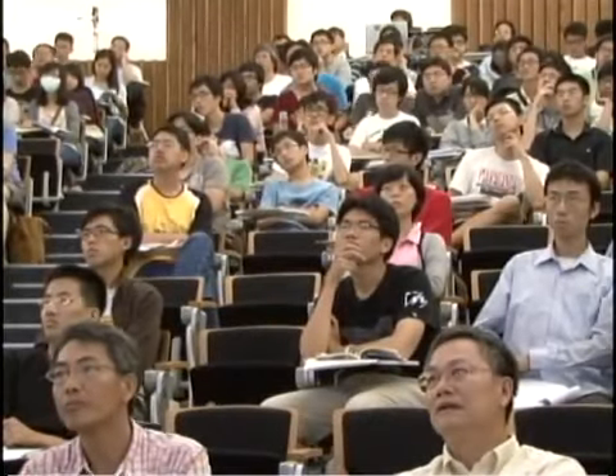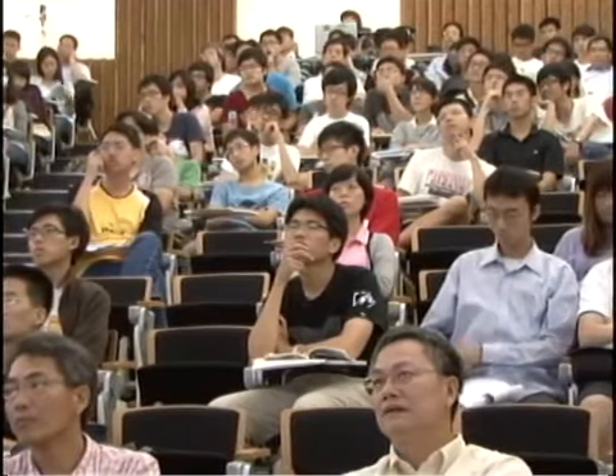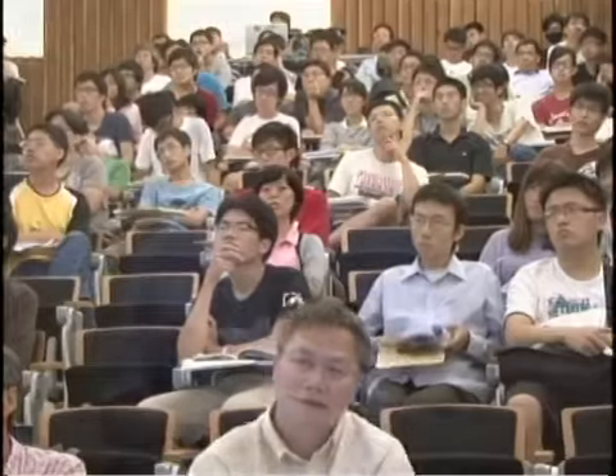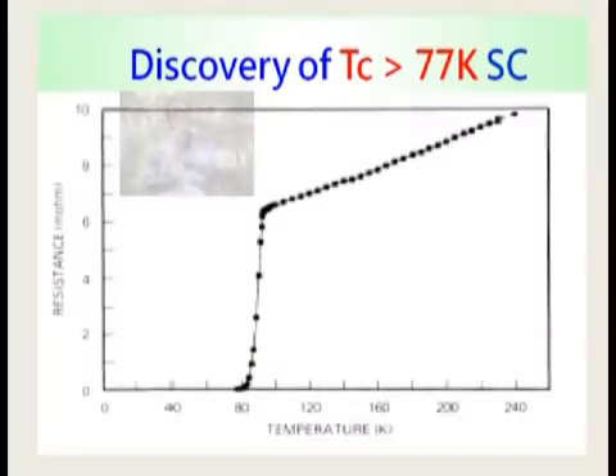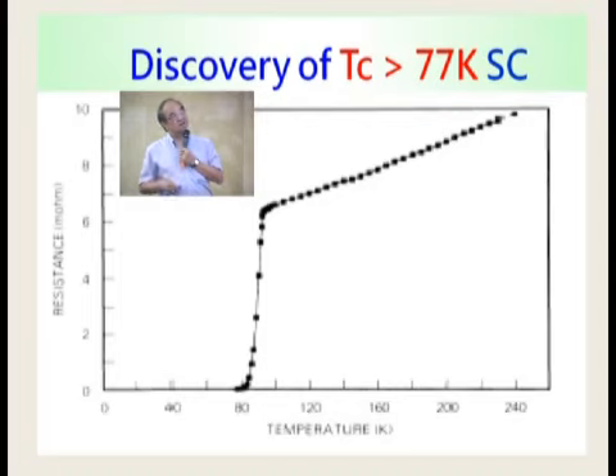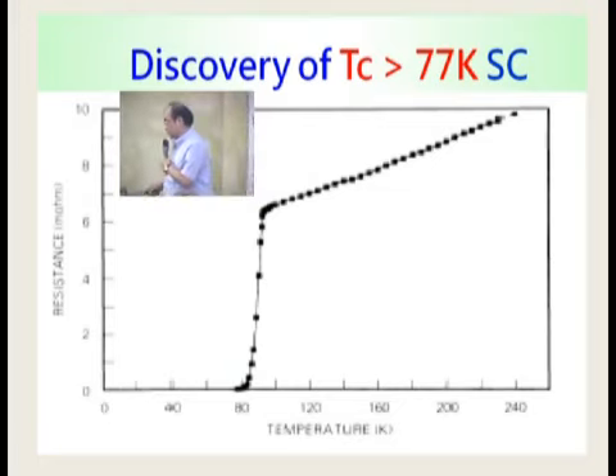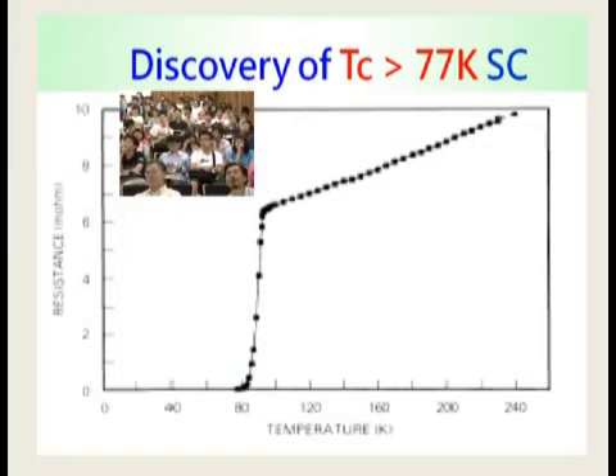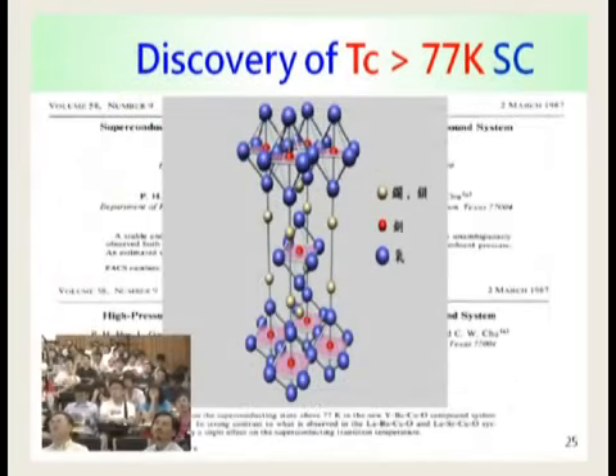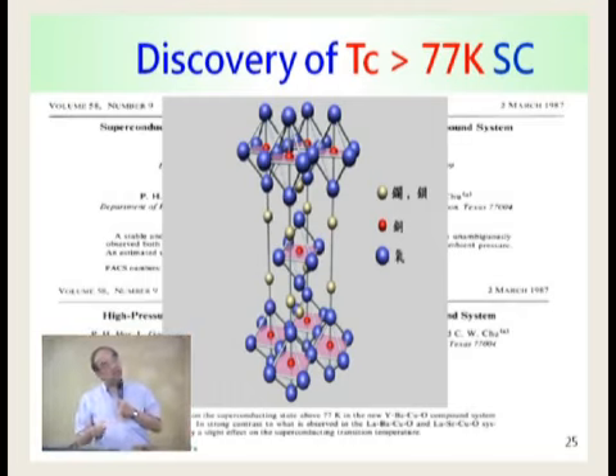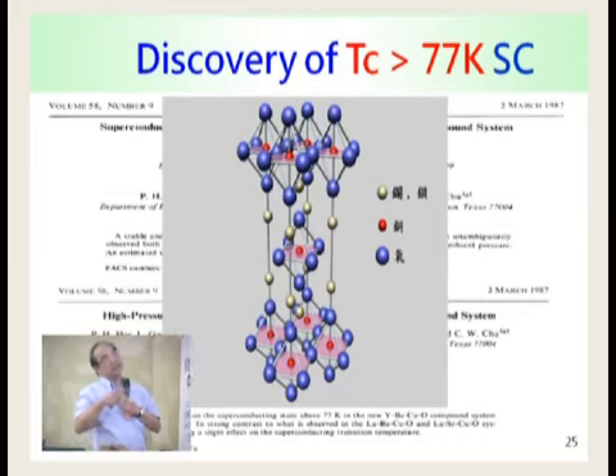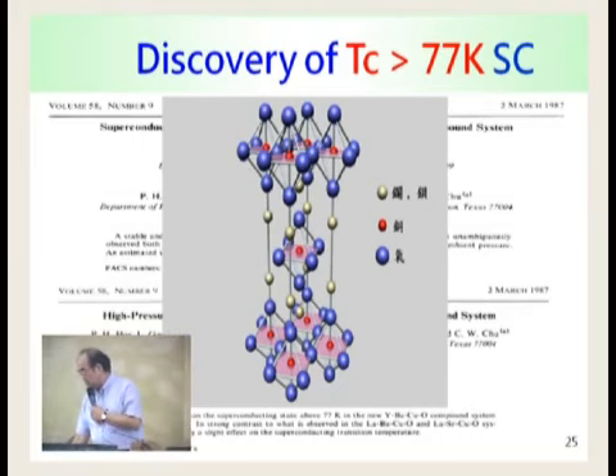And after measurement, we saw this. Okay, so that was 1987, about March, end of March. I remember March 27, and we did the measurement and showed this superconducting transition above liquid nitrogen. Okay, and that was the really exciting moment when we first saw this result. And of course, right after we measured it, we took the sample to Houston and confirmed it using the magnetic measurement. So we wrote the paper in a couple of days, and then sent it for publication. And that's the discovery of the first superconductor at about 77 K.